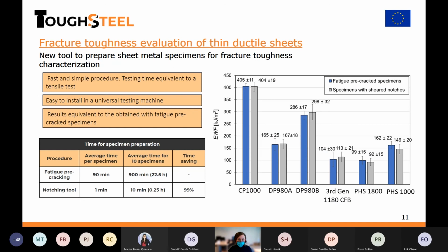And what's most important about this, first, is what I was saying. It's a fast method. We can see that for fatigue pre-cracks, we need at least 90 minutes per specimen, while here in 1 minute it's already done. And another important thing is that we have seen that it works for a variety of steels, from CP1000 to DPs, third generation, or PHS press hardened steels. So that's a good point to keep into account. This method is faster and allows you to apply the essential work of fracture methodology in a much faster way and without any specialized equipment.